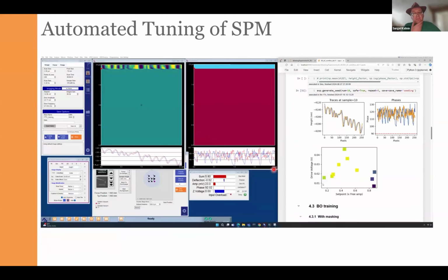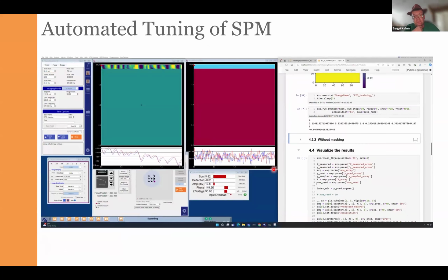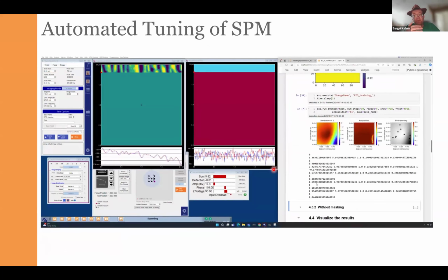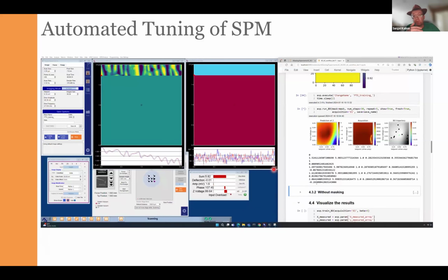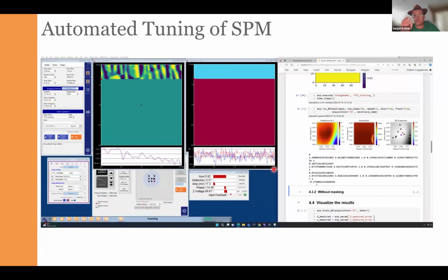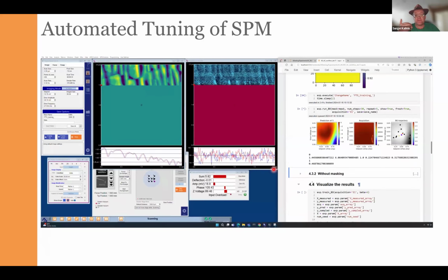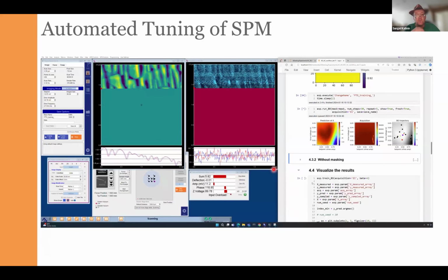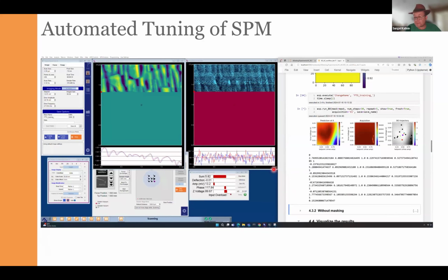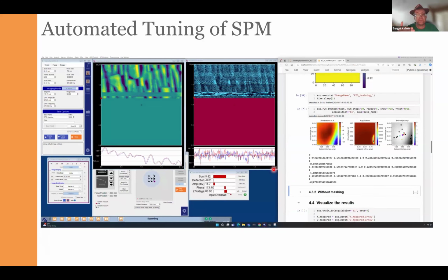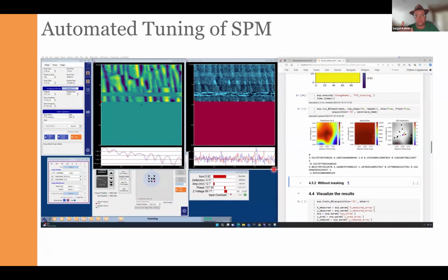The typical problem in microscopy is image optimization. Interestingly, if you have an atomically resolved image, image optimization is a relatively easy problem, because we can always see how sharp the atomically resolved image is, since we know what the ideal image looks like. If you want to optimize the microscope with mesoscale imaging, that's very complicated, because we don't have an unambiguous measure of how good the image is.